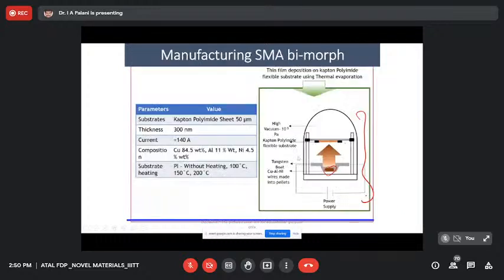Okay, so for our experiment, we went for a Kapton polyimide, and we went for a copper-based shape memory alloy in the boat, made in the form of a pellet. It's a kind of ternary alloy. We fused this pellet in a vacuum environment, kept it inside the boat, and heated the pellet so that there is continuous evaporation, and this evaporation deposits on the Kapton polyimide, which is being strained using a kind of arrangement over here.